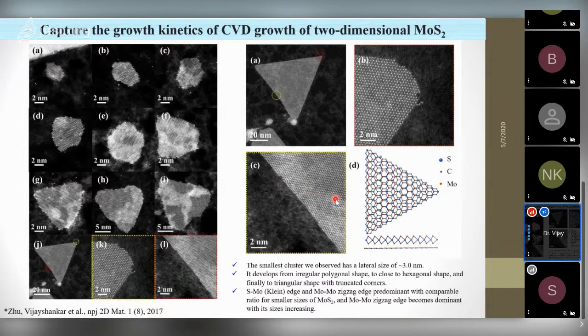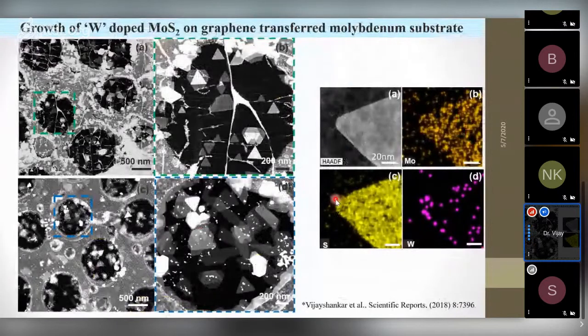With this, I have extended my research. Once it is found, like these are the possible things with molybdenum disulphide CVD growth, and already our group has explored atomic defects. So I wanted to try with an addition of new atoms. I wanted to introduce tungsten into molybdenum disulphide. Of course, I found monolayers. The monolayer growth was perfect. Then the EDS clearly says molybdenum and sulfur, so it's a MoS2 monolayer, and these are the tungsten atoms located around the edges of those monolayer